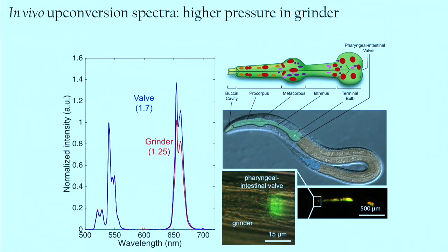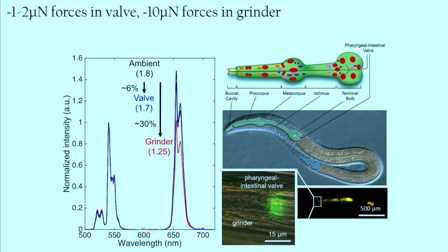Okay, so now we look at spectra. Here are spectra of nanoparticles right in the pharyngeal intestinal valve, so that's right where the worm is swallowing the nanoparticles, versus in the grinder. So you can see the red to green ratio is different, whether it's in the grinder or in the pharyngeal intestinal valve. And both of those have smaller red to green ratios than what you would find in ambient. And you can correlate that to our ex situ force measurements, indicating that there are roughly 10 micronewton forces within the grinder and about 1 to 2 micronewton forces in the valve.